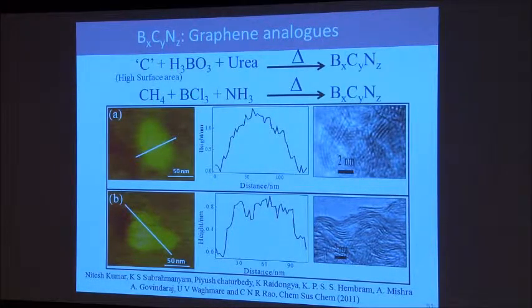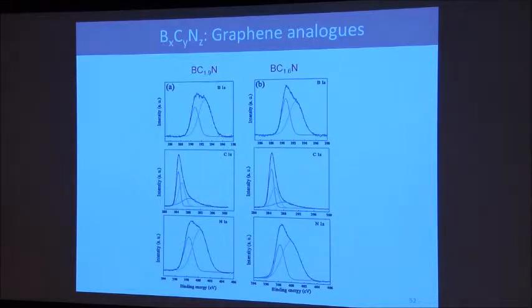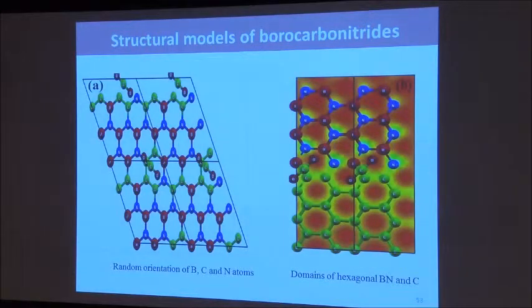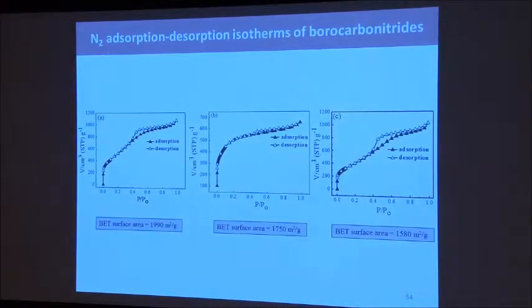You can also do it by gas phase reaction, but the gas phase reaction gives very low surface area material. By this solid state route of ours, you get high surface area material. I will not bother you with the details of characterization, how it has boron, carbon, nitrogen, as studied by X-ray photoemission and other means. The trouble with these borocarbonitrides is they can have rings of boron, carbon, nitrogen, but they can also have domains of carbon with domains of boron nitride. Both are possible, but most of the materials we have seem to have these extended structures of these rings, which is very nice. It is not completely homogeneous - sort of a composite, a combination of properties, but unusual properties. I'll tell you what I mean by unusual properties.